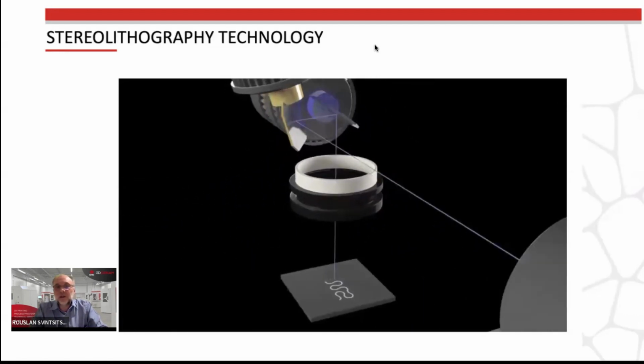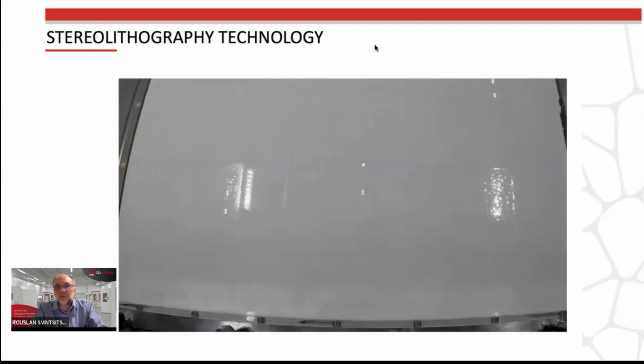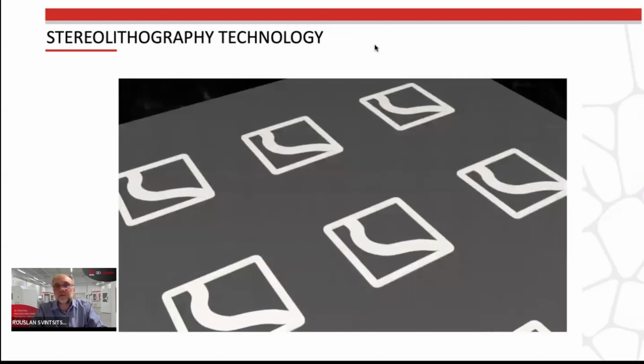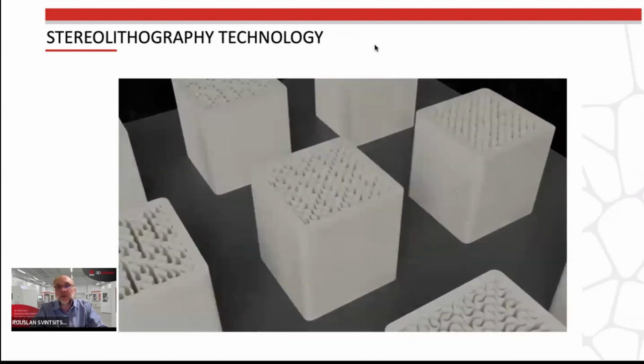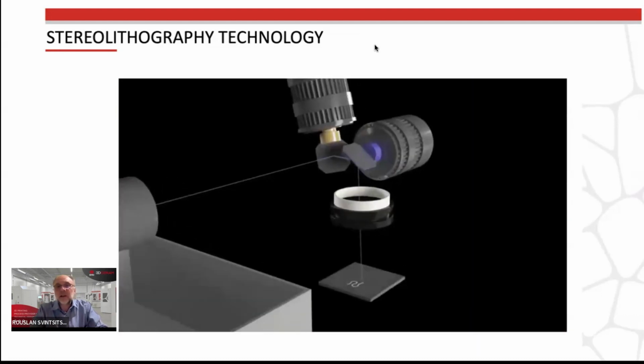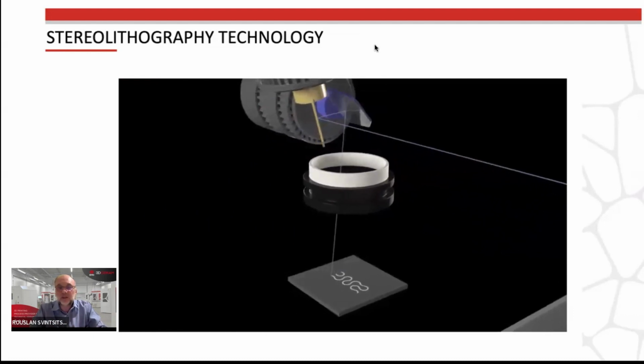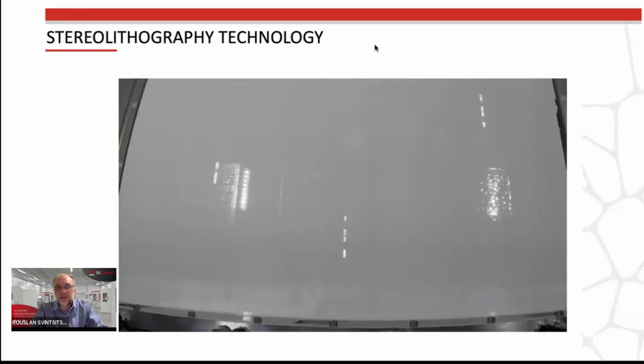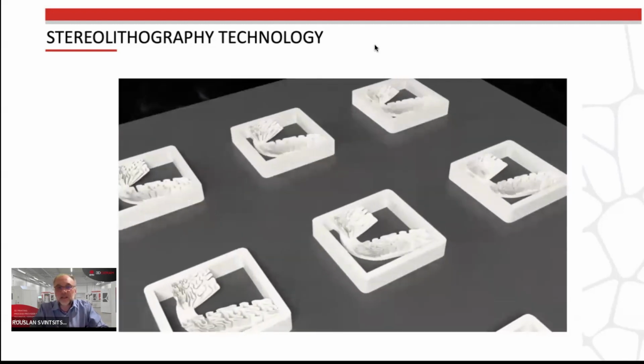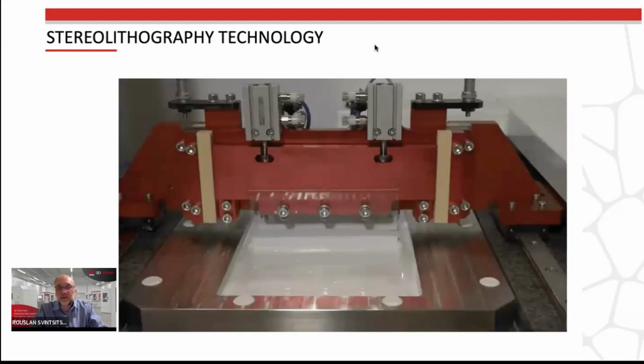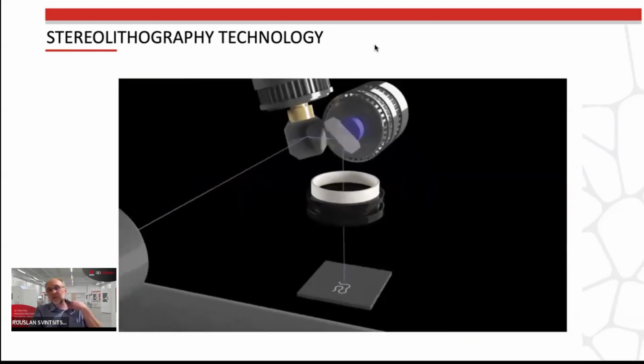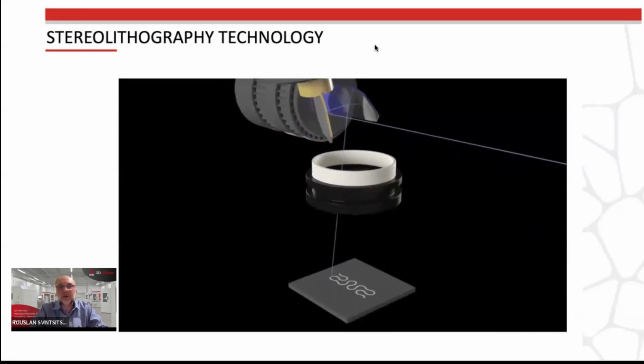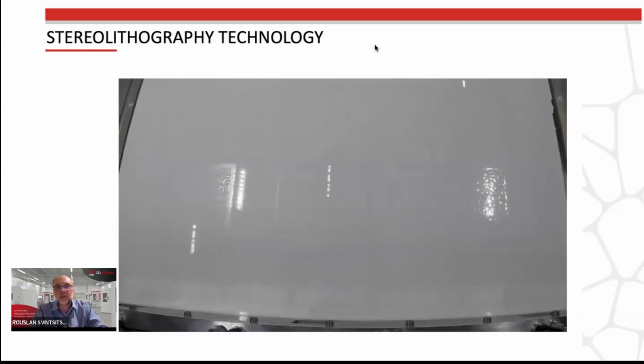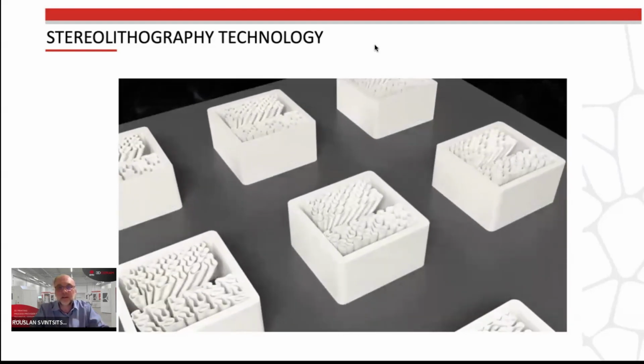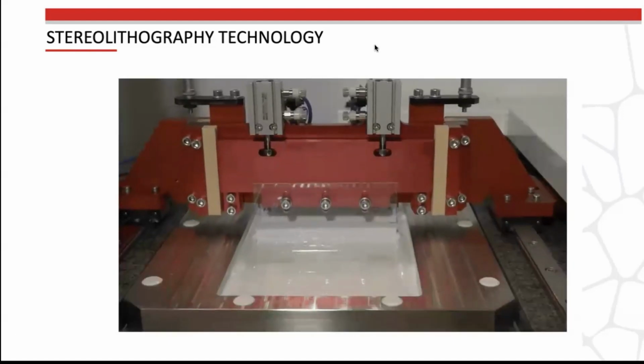How does it work? SLA is stereolithography. We cure with a UV laser installed above the printing platform the slurry, which is a mix of ceramic powder and photosensitive binder. Typically, you dispatch your layers of ceramic slurry, and you cure each layer in each particular location with this UV laser. You may already know some SLA technology in resins, maybe in metals, so it works in the same way. There are a lot of advantages of this technology compared to other polymerization technologies like DLP, but it's not the subject of this meeting. If you have questions about the advantages of SLA versus DLP, we can answer after this webinar.